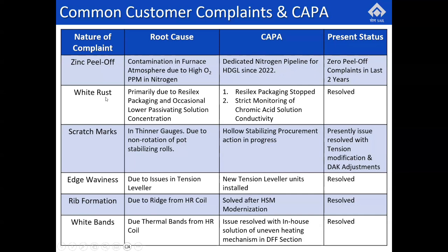White rust is one thing which plagued us around the last 2 years. Again, the root cause, as Nilanshu sir was saying, we found out that more in Resilex packed coils, we used to have more complaints of white rust. So we have done away with Resilex packaging due to several customer complaints throughout the country.